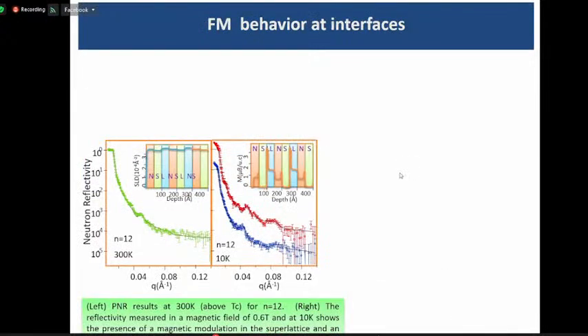Someone may think it's not an interface effect. Maybe you made some mixture at the interface, and that mixture can make the ferromagnetism. So I did some neutron reflectivity measurement. This data shows that at the interface the magnetic signal is very high, like this.